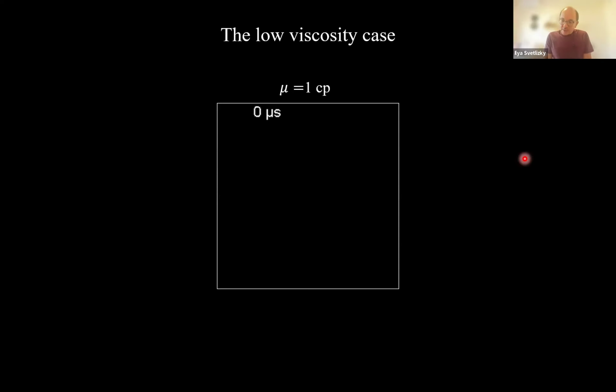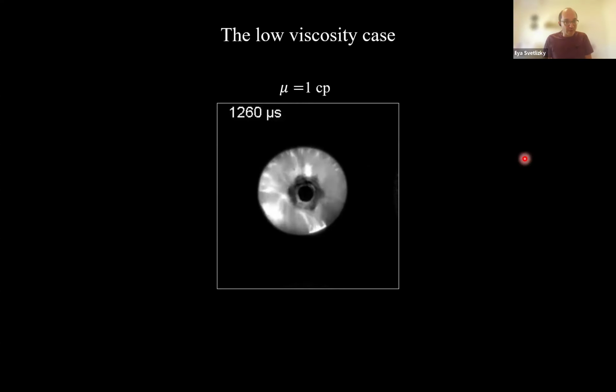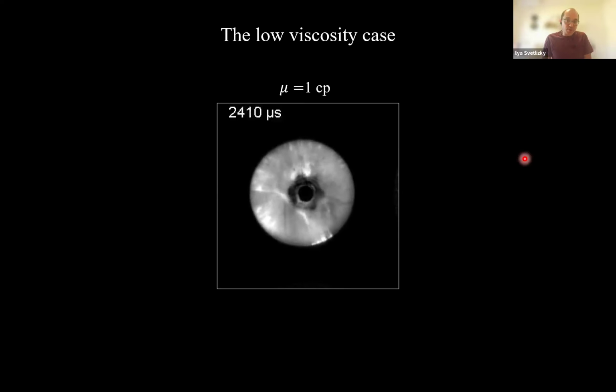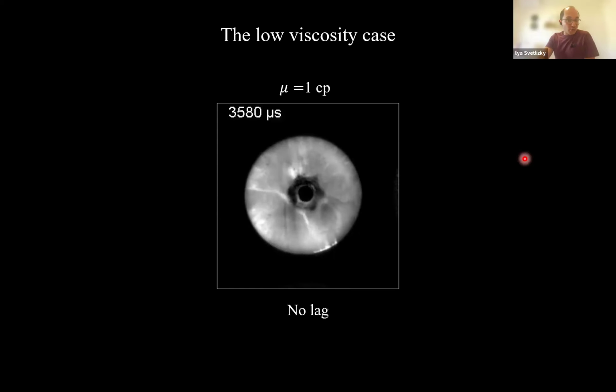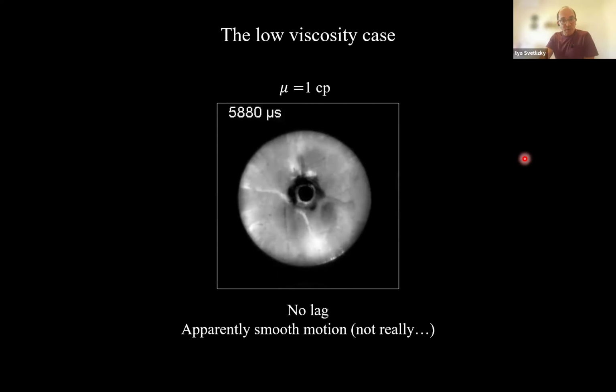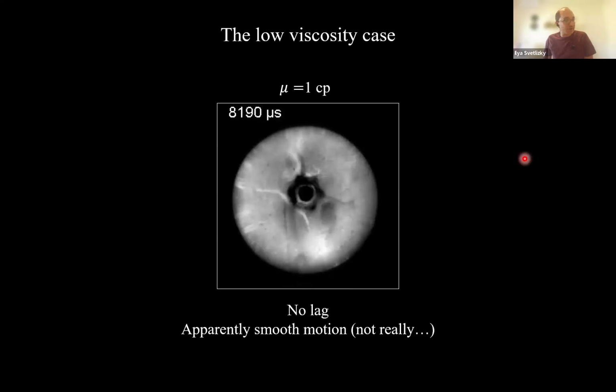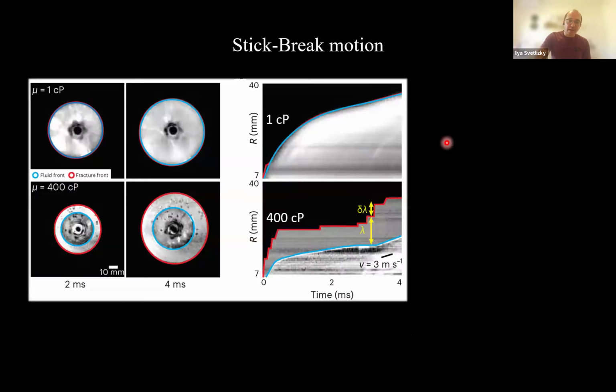So as I said, we have a control parameter, which is the viscosity. The previous experiment was at 400 centipoise. And now I'll show you a movie of what happens when you just use water, 1 centipoise. When you run the experiment, what you see is that there is almost no lag, or it's very difficult to find any lag between the crack and the fluid. It seems like very smooth motion, but if you're careful enough, even the 1 centipoise has some dynamics along the transverse direction. So again, we take a couple of snapshots, we track, we plot the radial intensity versus time. You can see the 400 centipoise: big jumps, large lag. There is no lag, there are almost no jumps with pure water.